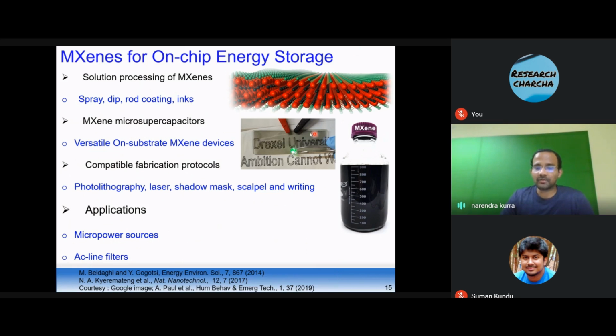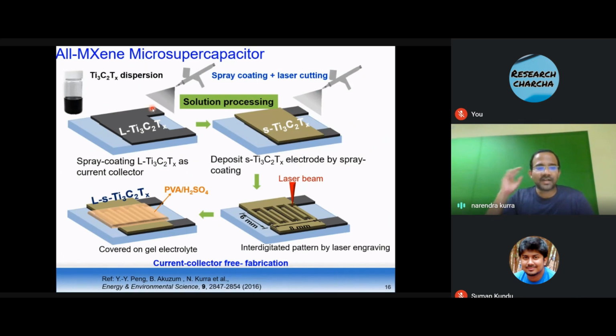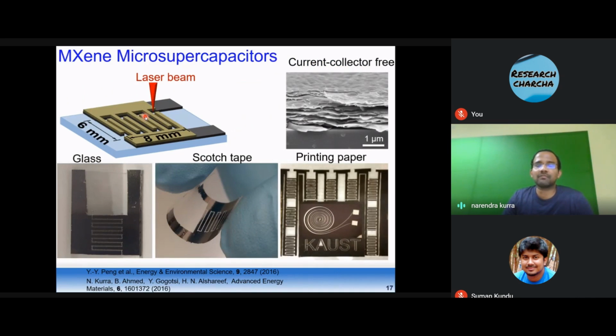And we show that MXene can be used as transparent conducting electrodes. As you can see here, a transparent MXene coating can light an LED. One of the strategies is that since MXene exhibits metallic conductivity, we don't need external metal current collectors. As synthesized MXene has a flake size, lateral dimensions, typically 1 to 2 microns. We spray coat large flakes of MXenes, followed by small flake MXenes, where we probe sonicate the MXene solution to get small dimensions around 200 nanometers, which is good for ion diffusion, followed by using laser engraving to make this interdigitated electrode architecture, and then placing the gel electrolyte. So this way we develop current collector free MXene micro supercapacitors.